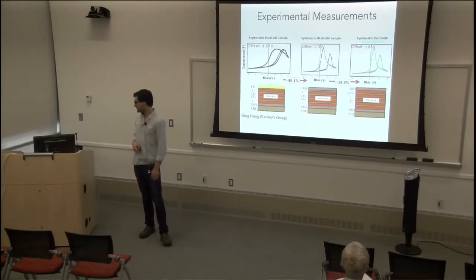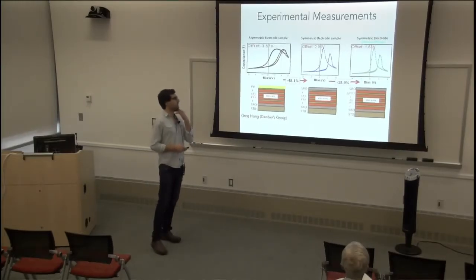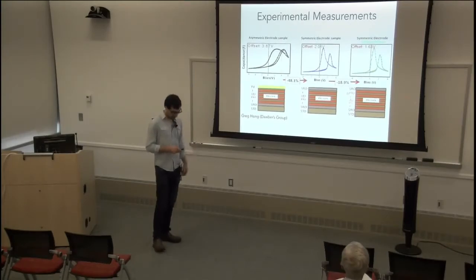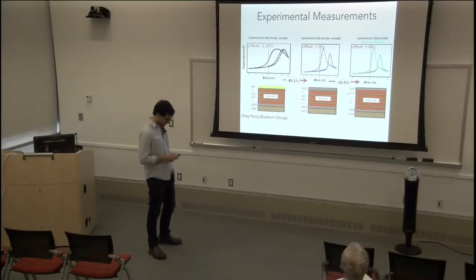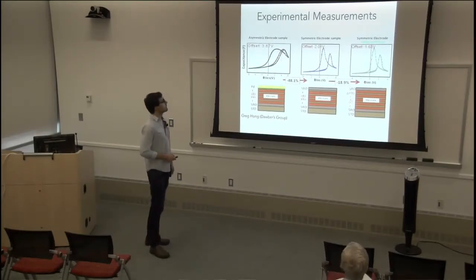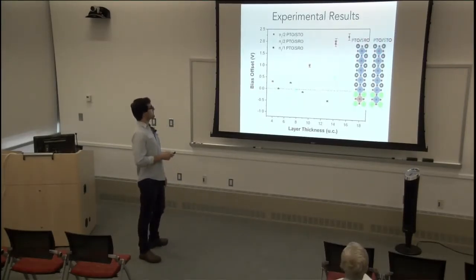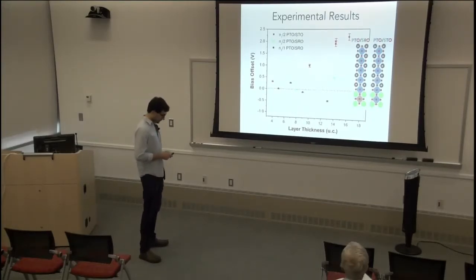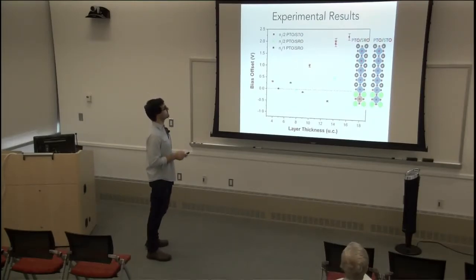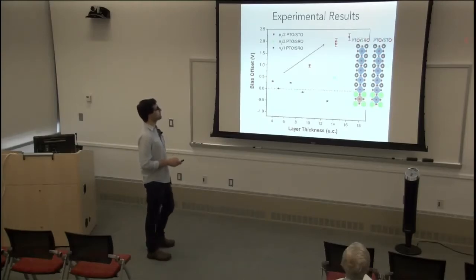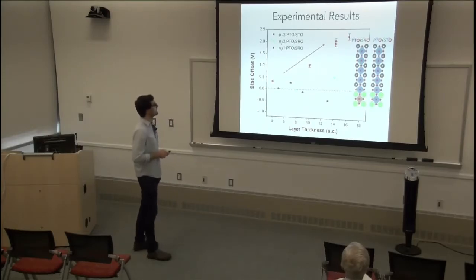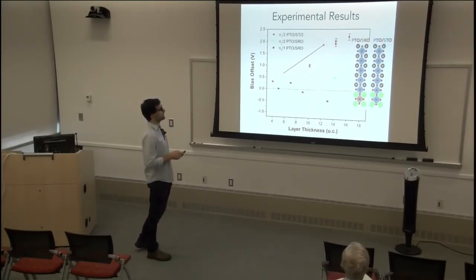And this is only for one specific superlattice. So what we want is a trend. We want to understand what's happening as we vary different things. So here are the experimental results where I have the bias versus the lead titanate layer thickness. In red, I have the lead titanate strontium titanate, which is this superlattice here. And what's shown is that as I increase the number of unit cells of lead titanate, the bias keeps increasing.